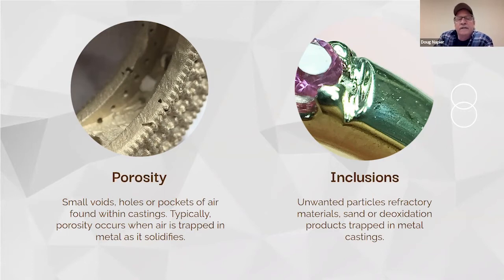So one of the things you have to do is familiarize yourself with the problem of the casting surface. Is it true porosity, shrinkage porosity, or gas porosity? Or is it something a little bit different, like the one on the right is actually inclusions. And what that is, things that are getting into your metal. Usually it's investment. Some of the older resins, it might have been resin residue that accumulates in certain areas. So familiarize yourself with troubleshooting what the real problem is. Don't just say, I cast this piece and I'm getting porosity, so who do I call? So do a little bit of investigating. If you got a microscope, kind of dive into it and see exactly what the problem is.